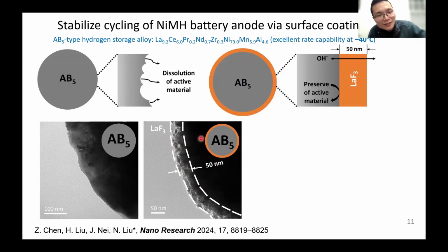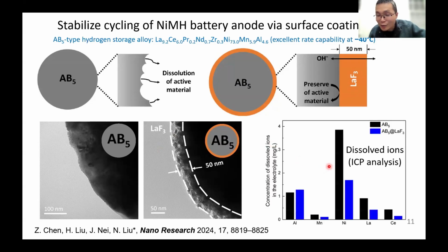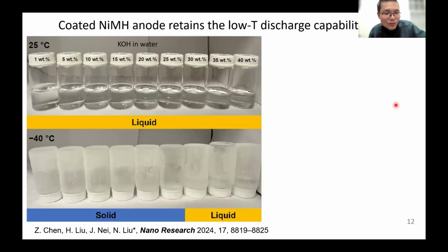So it has good adhesion, and you can also make it very uniform and thin. After coating lanthanum fluoride, we tested the solubility again, similar to the zinc. You can see that with the coating, the amount of nickel, lanthanum, and cerium dissolved into the electrolyte is much suppressed. That indicates the coating is indeed working. With the coating, you may think, will that make the low temperature performance worse, because it may slow down the ion transport and block the ions from reacting with the particle, right?